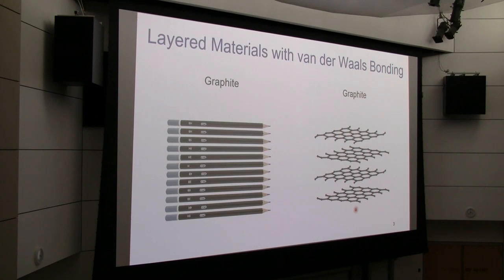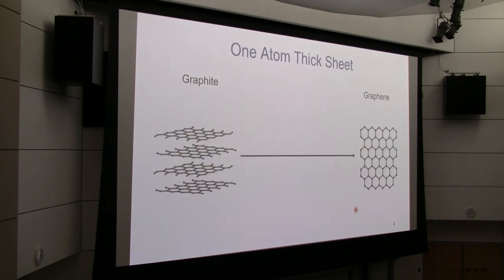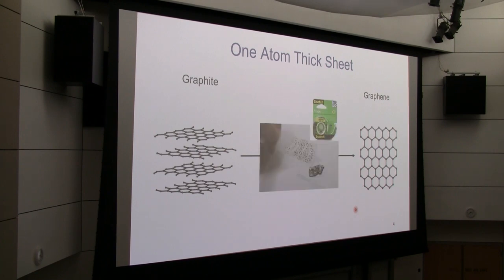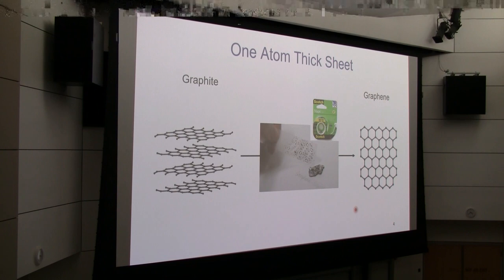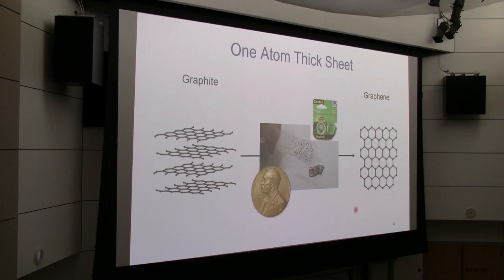maybe we can get to a single atomic layer of this material. And indeed, people were able to achieve that. They can actually exfoliate graphite into single layer graphene by just using Scotch tape. So what you do is you just use Scotch tape and exfoliate multiple times. Then by luck, you'll get all kinds of thin layers like monolayer, bilayer, trilayer, and so on and so forth. And the discovery of this way to create atomically thin layers got a Nobel Prize more than a decade ago.